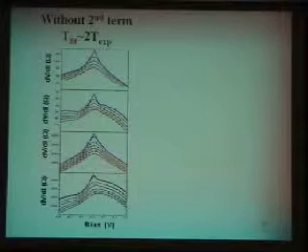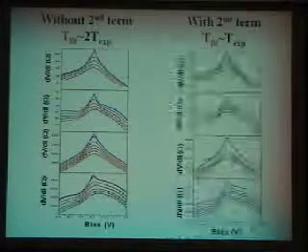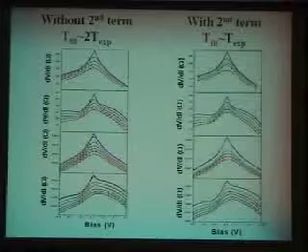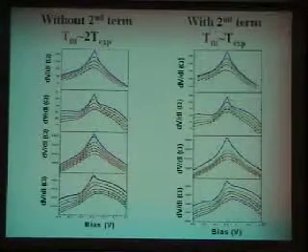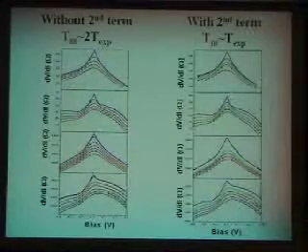So here it is. Here is the fit without the second term. You see the fit is excellent without the second term. You don't need that damn second term, so forget about it. But there is this problem that the fit gives you twice the experimental temperature. Well, you forget about it. You fit it with the second term and then it's good. No problem. So you don't do what everybody does in this field; you include the second term.